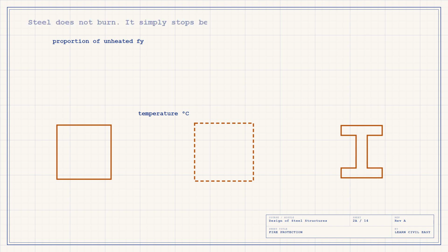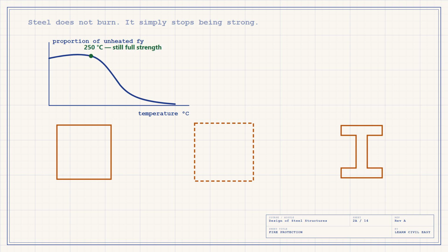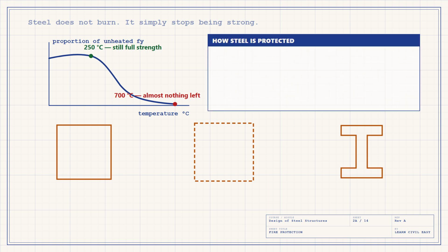There was a time when people believed uncased iron was fireproof. It is not. Heated iron distorts badly and becomes unfit. Watch what heat actually does. Plot the strength of steel as a proportion of its unheated yield stress. Up to about 250 degrees it holds. It even rises a little and then it falls away. By 700 degrees there is very little left. Steel does not burn, it simply stops being strong.